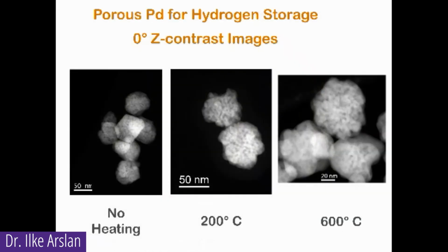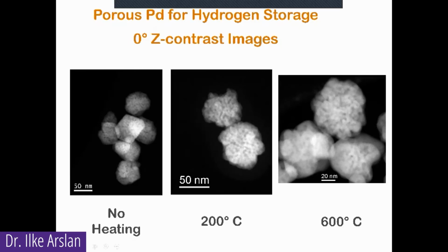And then while I was at Sandia, we started looking at hydrogen storage, and we were looking at these porous palladium particles. What we wanted to understand is their stability and how well they could store the hydrogen. When hydrogen went into these particles, it would expand the lattice. And we wanted to be able to store the hydrogen without these pores breaking down and still fairly close to the surface. So we want a high surface area. We want the pores highly porous so that there's a lot of space for them to go into, but we want them to be stable.